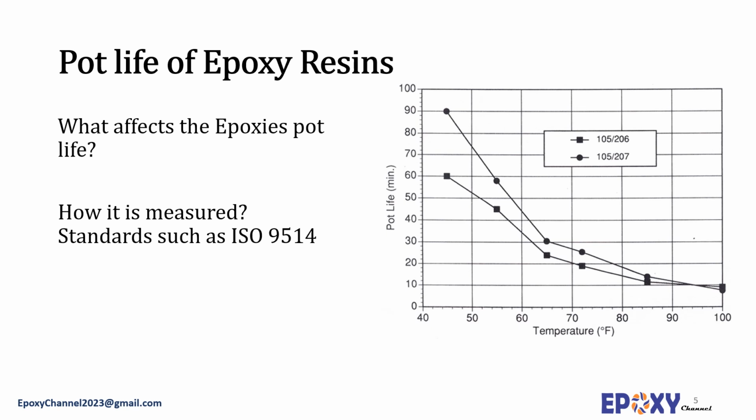The pot life of an epoxy coating depends on a number of factors. One of the well-known factors is temperature. A higher temperature of the mixture environment will speed up the chemical reaction rate and so reduce the pot life. The effect may vary from product to product, but a 10 centigrade rise in temperature can halve the pot life. Therefore, storing the epoxy resins and hardener agents in cool, sheltered places around 15 centigrade prior to use, as well as working at low ambient temperature, is recommended to prolong the pot life.